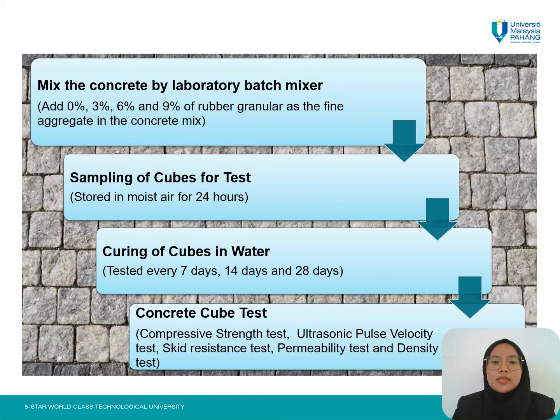We will mix the concrete with a laboratory batch mixer. Sampling the cubes for test, store in moist air for 24 hours. Then we will cure the cubes in water for 7 days, 14 days and 28 days. Then we will test the concrete cubes with the compressive strength test, ultrasonic pulse velocity test, skid resistance test, permeability test and density test.